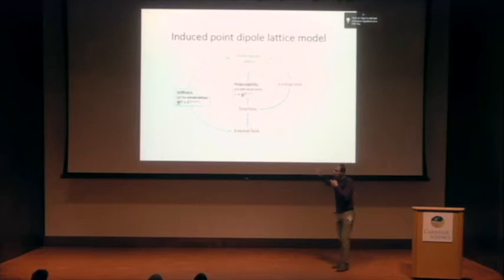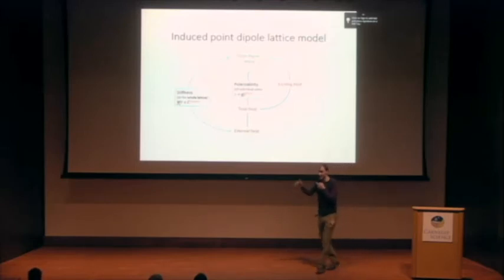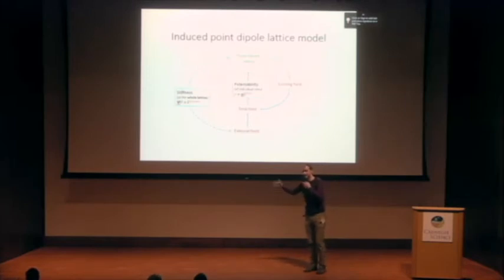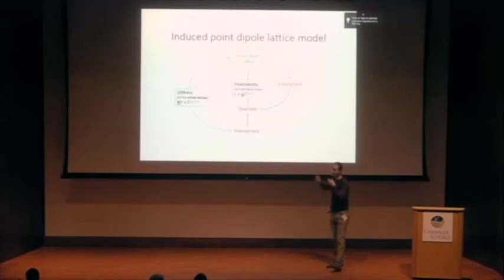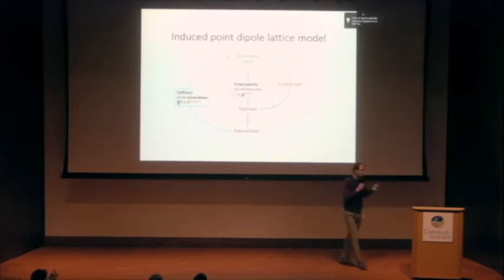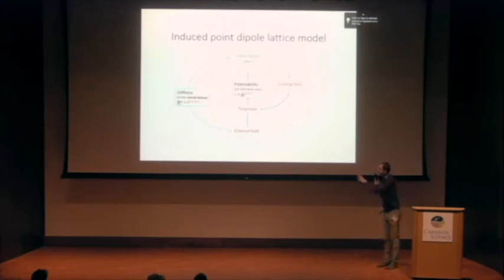But the whole situation is more complex because we have a feedback on the right. Dipoles create fields on themselves. So the lattice creates fields on itself. This is called the exciting field, due to Ewald. This exciting field sums up with the external field, and the total field, via the individual polarizabilities of the sites in the cell, makes the resulting dipole pattern. So the idea is to solve this model, to vary polarizabilities, and to look at what emerges from that.